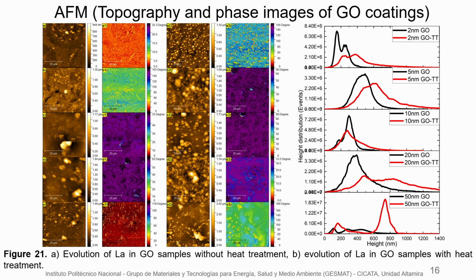This is for the samples with no thermal treatment. For the samples with thermal treatment, we can see that a lot of grains appear on the surface for all the samples, and in the phase image, we can see some differences in the contrast, and this is related to having different materials on the surface.